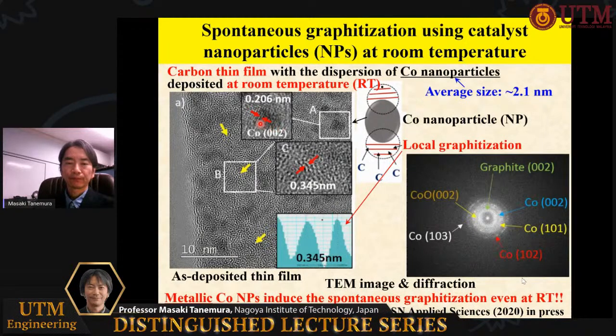This is a TEM image of the film. You see the mixture of the black and white contrast. The black contrast corresponds to the cobalt nanoparticles, and the white contrast region is a carbon matrix. This shows an enlarged image of the box A, indicating the cobalt lattice of 002 plane.